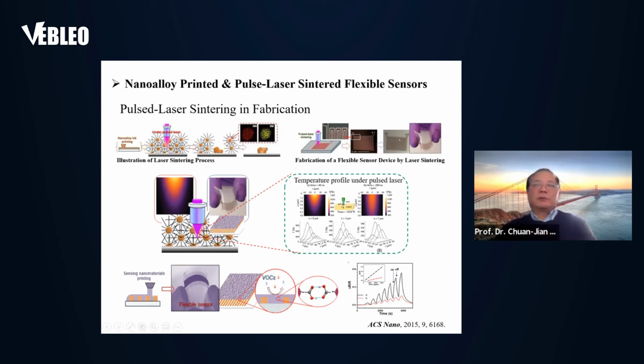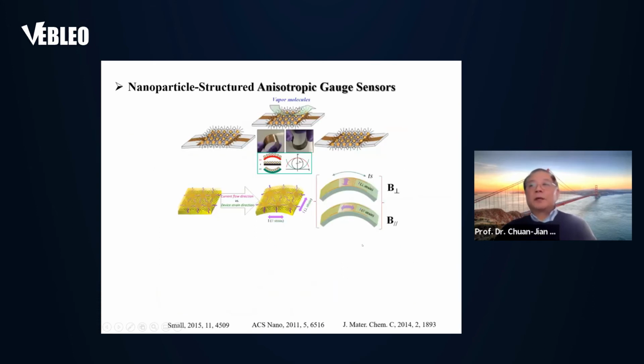So we made some devices on plastic substrates, like PET. We can also make this on a paper substrate. And if you load it with sensing film, you can see the response. Because of the fiber structure, the sensitivity is so much higher than on a PET substrate. That's a very important discovery.